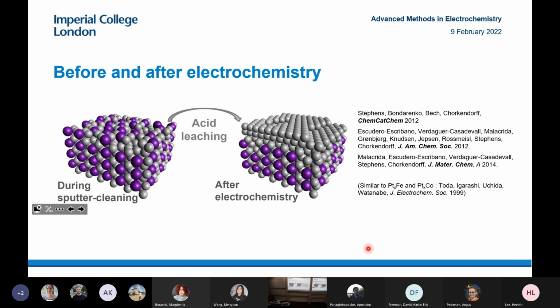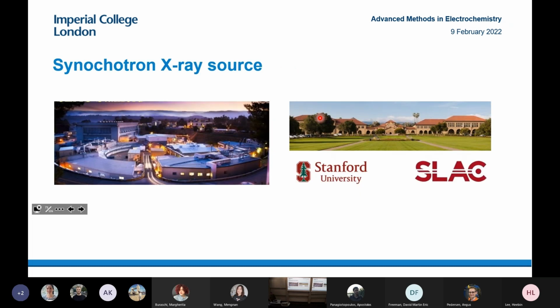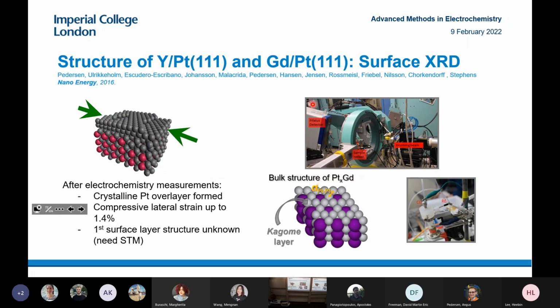So the kind of picture we had was that you have a platinum rare earth surface, then you expose it to acid, and then you leach out the rare earth. And you have a thick platinum overlayer. So then we went to a synchrotron in Stanford to try and understand what happened. Back in Denmark, we made essentially something that resembled a platinum alloy single crystal. We evaporated a lot of yttrium or gadolinium onto a platinum single crystal and annealed it. We had a really thick layer of the alloy.